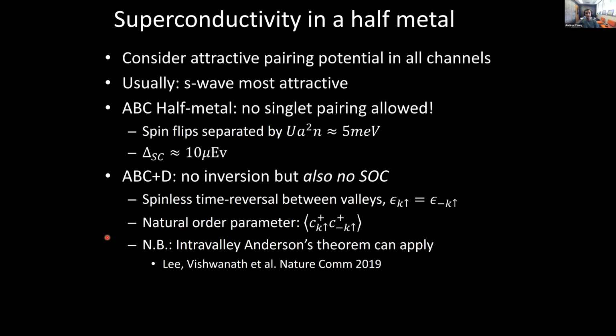So you can consider, if you have an attractive pairing potential in every channel, usually S-wave pairing is the most attractive, and so most superconductors have essentially S-wave symmetry. But if you already start from a half metal, then you certainly can't have spin singlet pairing. You don't have the other spin. A way to think about this is that exchange is very strong. Spin flips are separated from the ground state by some energy scale that might be 5 millielectron volts or 50 Kelvin in scale, but the superconducting gap is only 10 microelectron volts, so not very big.